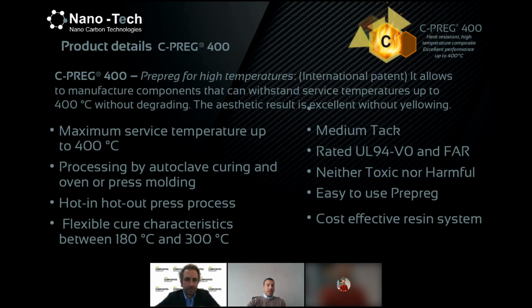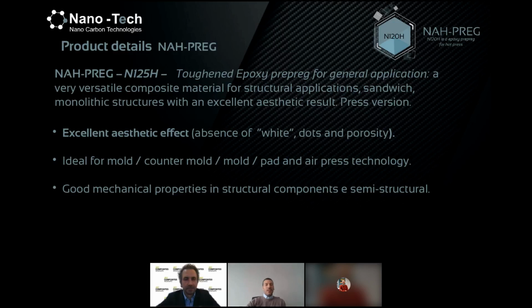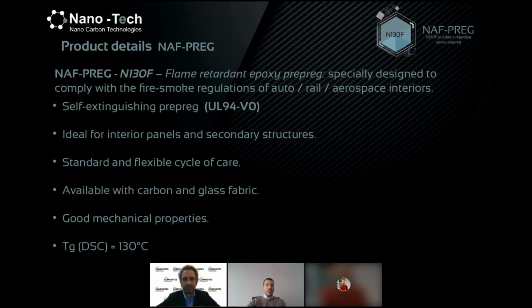Here there is the Cpreg that we will talk about in the rest of the webinar, so I will go further. And we recently developed a toughened epoxy prepreg for general application, but in particular for press molding. The current cycle is 15 minutes at 150 degrees. So you can have an aesthetic component without white dots and with very low porosity, and you can speed up your production process compared to the normal autoclave processes.